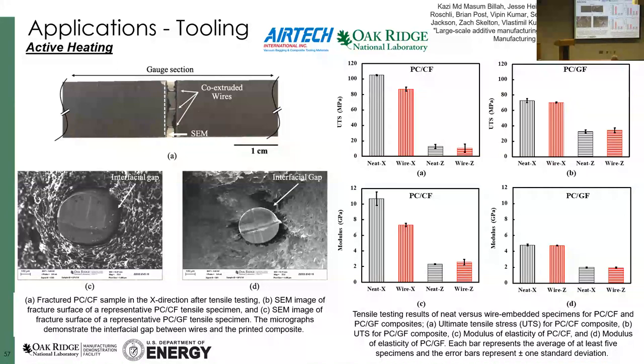We didn't condition the material. We didn't do any surface prep for the wires. So basically there was no good adhesion between the matrix and the wire. And then it created interfacial gaps and interfacial sites that, as you can see over here, were really intense because there is no load transfer actually. There was no load transfer. The matrix just started to propagate the crack and it separated the matrix, but the wires are still tacked on there, right? It is not the end of the world. If your tool will not need more than 60 megapascal UTS or 7 gigapascal on the stiffness, you are good, right?